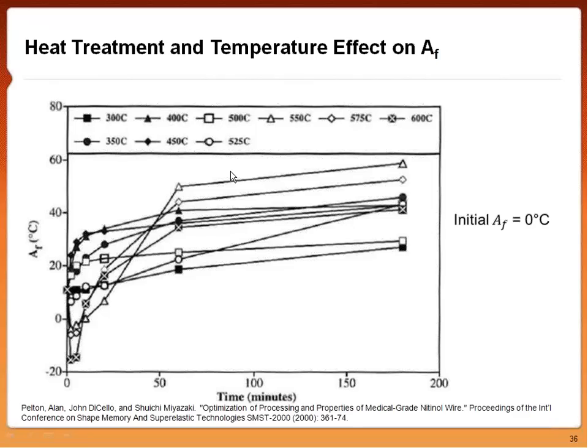To do that, when we want to pick the correct time and temperature, we look at this graph over here, which is a function of our AF, taken from a sample that initially starts at 0 degrees Celsius and moves in a time fashion over here. We can see that with the higher temperatures we go and the lower times, we're significantly increasing our AF. But again, if we look at the path graph, we're detrimenting our ultimate tensile strength. So the point of this graph is we need to pick a balance.